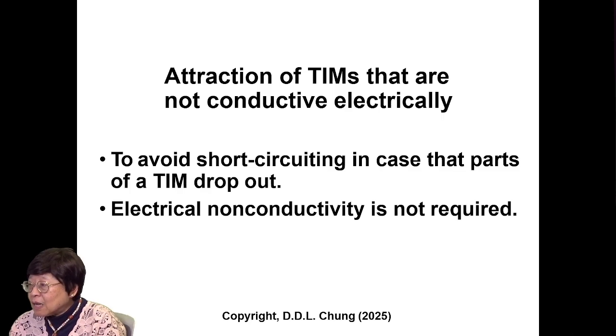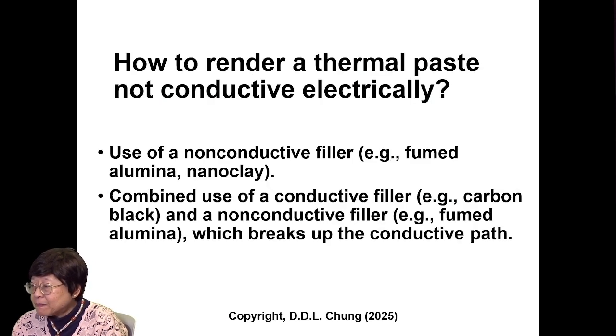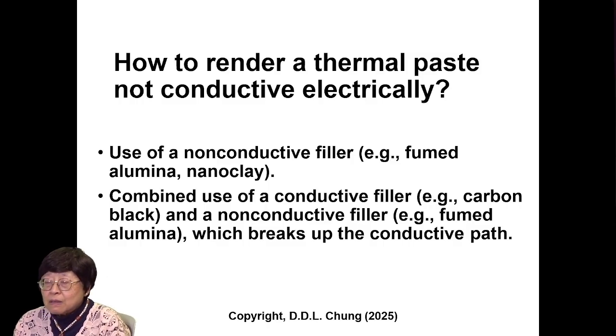Attraction of TIMs that are not conductive electrically is to avoid short-circuiting in case that parts of a TIM drop out. However, electrical non-conductivity is not required for TIMs. Now, how to render a thermal paste not conductive electrically? Well, one is to use a non-conductive filler, such as the fumed alumina or nanoclay. Another way is the combined use of a conductive filler, such as carbon black, and a non-conductive filler, such as fumed alumina, and the non-conductive filler breaks up the conductive path.